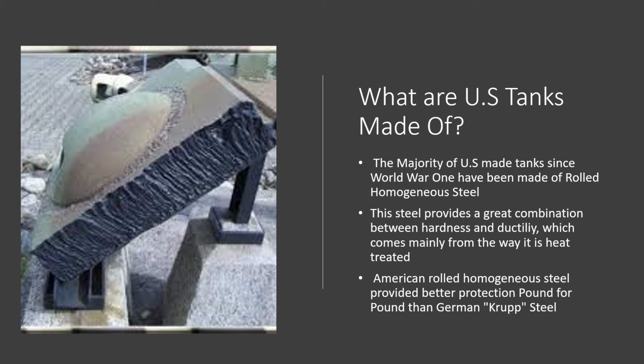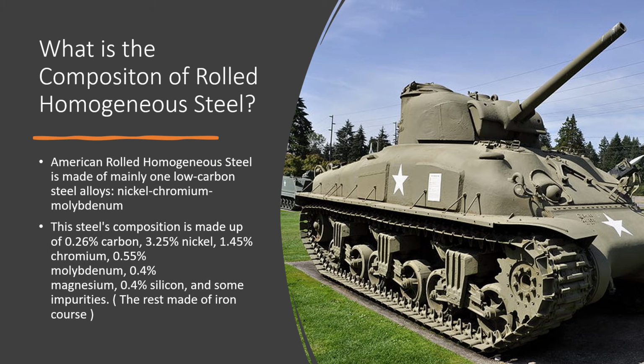And this rolled homogeneous steel often proved to be better than enemy steels used in their tanks, specifically the German Krupp steel, which often was too brittle to be effective. Now, rolled homogeneous steel is mainly made of a low carbon steel alloy, which was mainly nickel, chromium, and molybdenum.